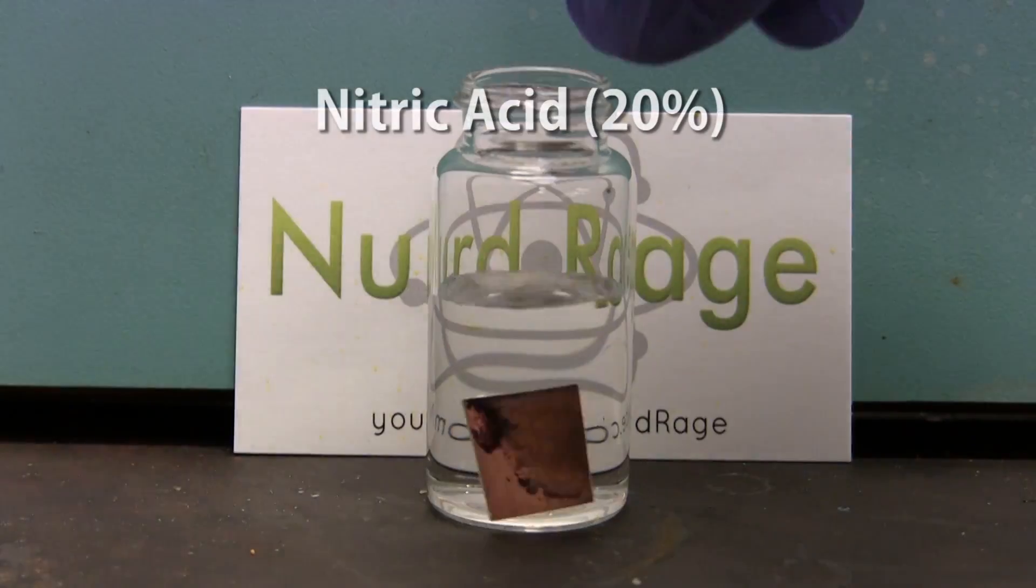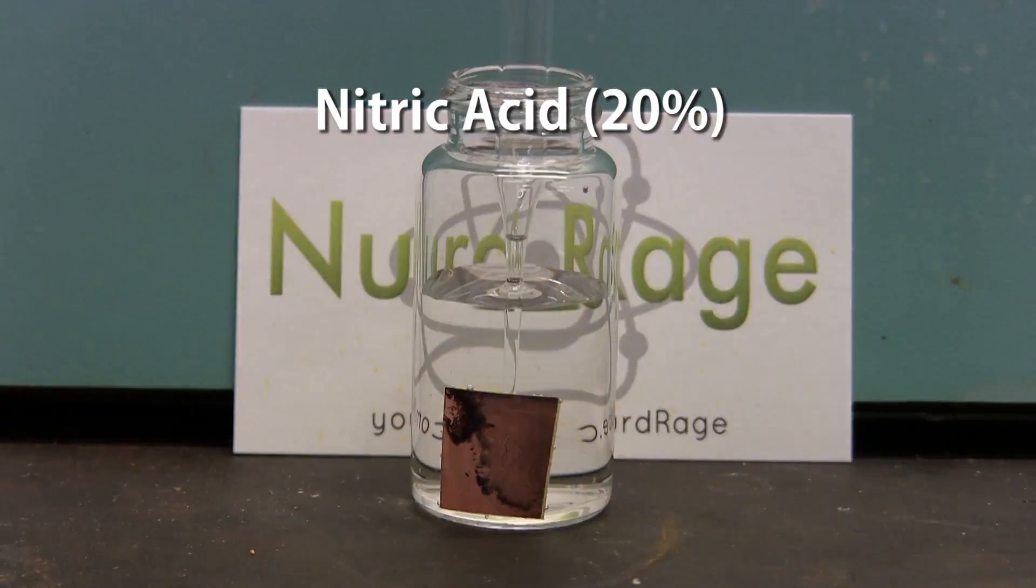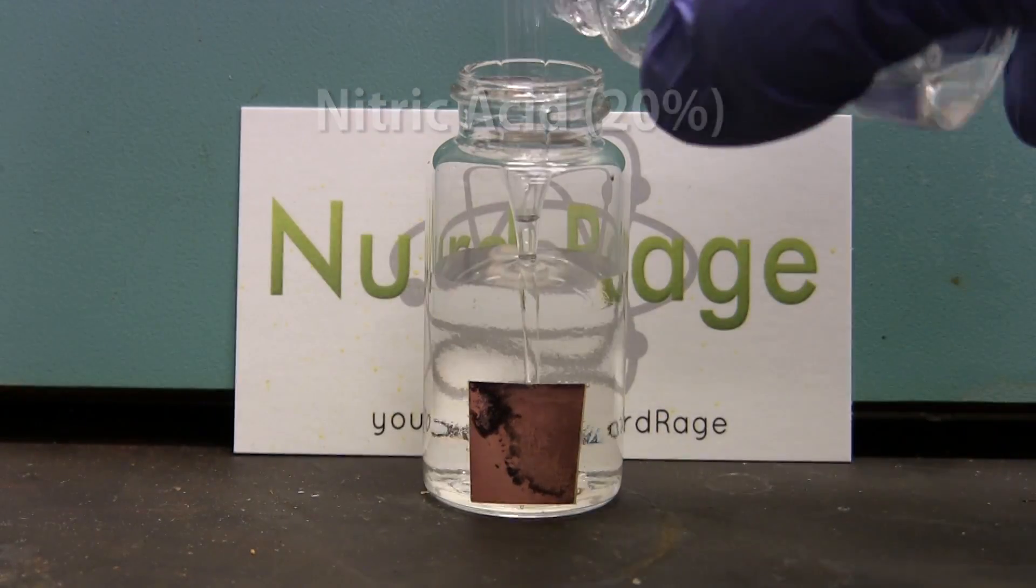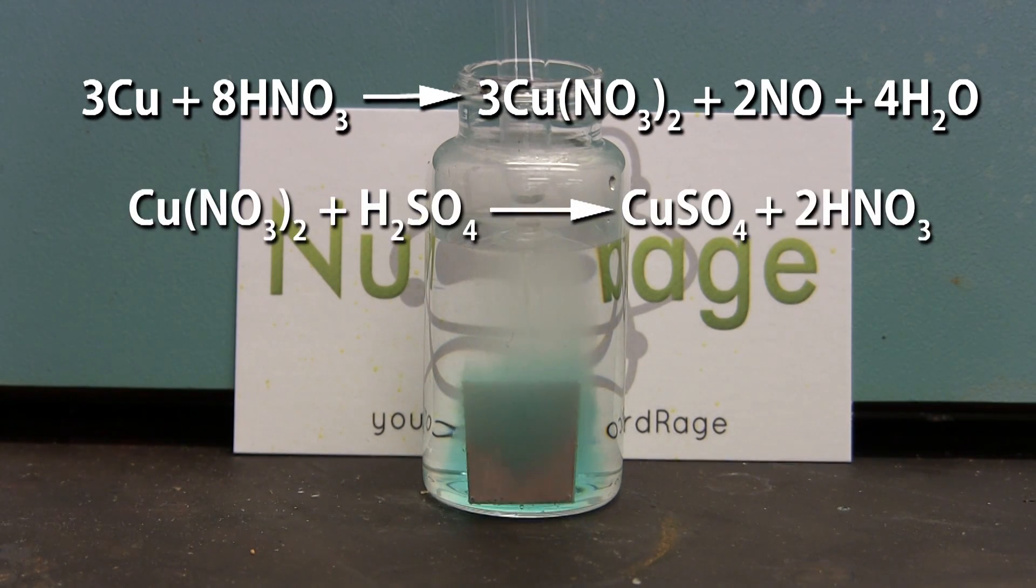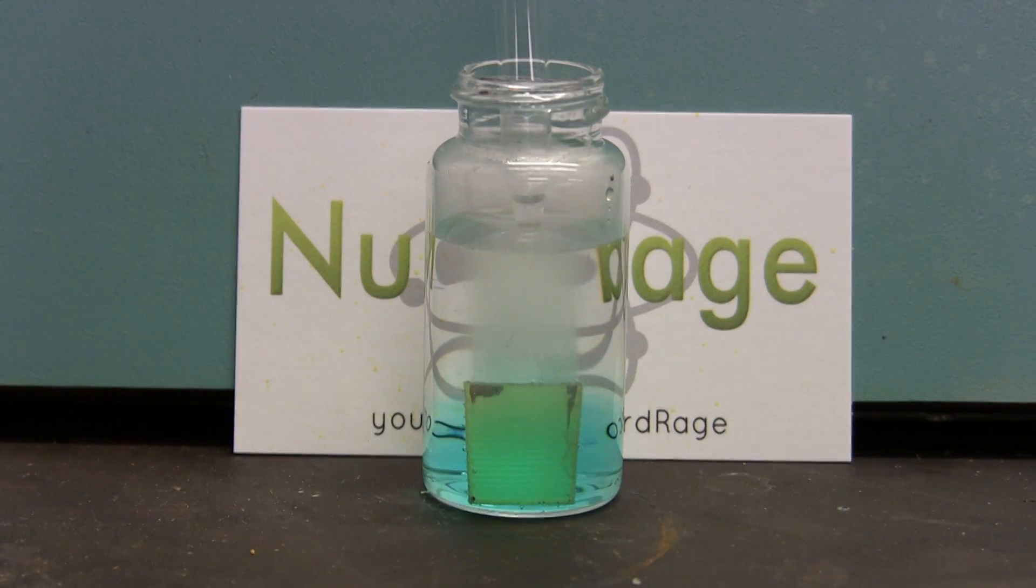The nitrate family of etchants begins with the simplest nitrate source, dilute nitric acid. This reacts with the copper to produce copper nitrate and nitrogen monoxide. Nitrogen monoxide is quite toxic so this must be done outside or in a fume hood. When the etchant stops working it can be boosted with sulfuric acid to reactivate the remaining nitric acid. After all the nitric acid is depleted the etchant is dead and the copper sulfate can be electrochemically recycled. Unused etchant can be stored indefinitely without losing strength.